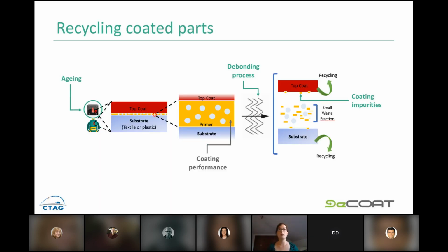Another factor is the remaining coating impurities, because it's impossible to have a purely efficient system with 100% removal of the coating. So there are always little impurities of the coating remaining in the plastic. And these impurities can also affect the performance of the recycled material. And finally, the recycling cycles themselves. I mean, it's not the same to recycle the parts once as twice or several times. So we also have to assess that in order to ensure that this approach guarantees circularity at the end.